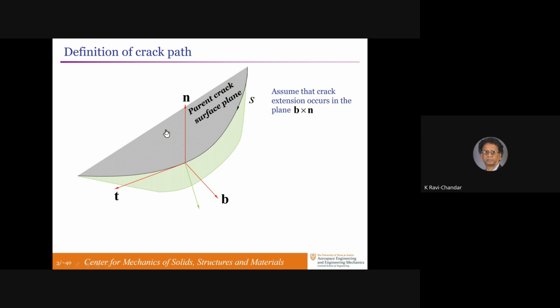So you need to go back to classical fracture mechanics, set up a framework for describing such cracks and then asking for the crack criterion. So think that you have a planar crack, what I call the parent crack. That's in the black shaded region, and this line here is the termination of the crack, so it's the crack front. You can establish a coordinate system here. N is normal to the fracture surface of the parent crack, and T is tangent to the crack front at every point. It's a three-dimensional object, so N and T can vary as a function of position along the crack front. There's a third direction in this triad, and we'll call that B, which is normal to both N and T.